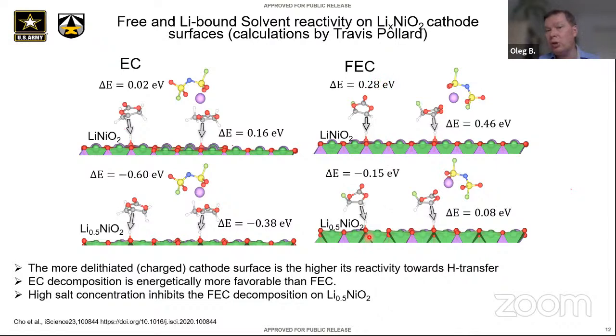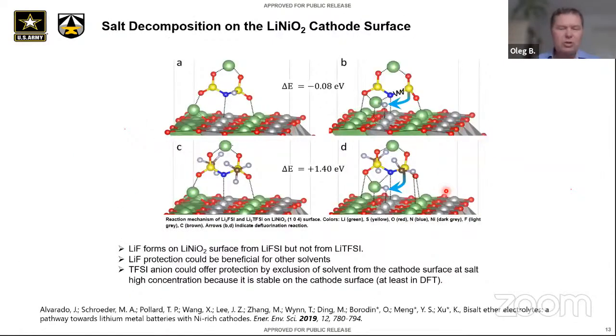However, once you removed about half of the lithium, then that reaction becomes energetically favorable, and you need to go to very high concentration, with FEC being actually all of them at the cathode surface coordinated to the lithium, then it will be stable. So that's an unpretty picture, which says that in the majority of the realistic cases where we want to push reactions, we unfortunately will have decomposition and have to rely on the decomposition products to be stable.